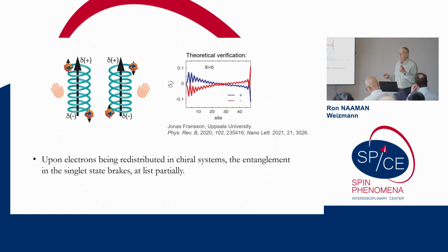So now, at least as a transient, you have spin polarization that accompanies the charge polarization. In the case of the 2D electron gas, there is an RKKY effect that stabilizes these spins, and therefore they are stuck there, and we can measure the anomalous Hall effect.